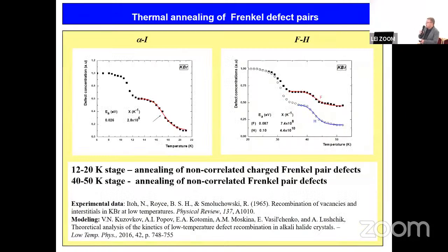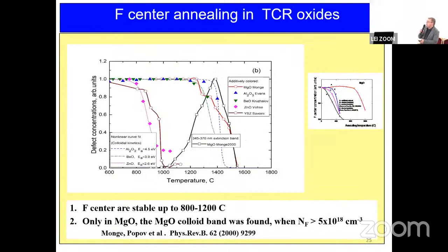We know from the literature that thermal annealing of these defects occurs at very low temperature. So we tested our model using stages of the thermal annealing with different concentrations, measured by optical density or by EPR. So the model works well. Then we applied this model to materials important for fusion applications.